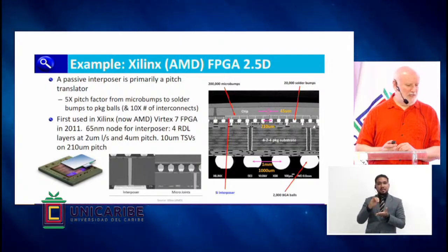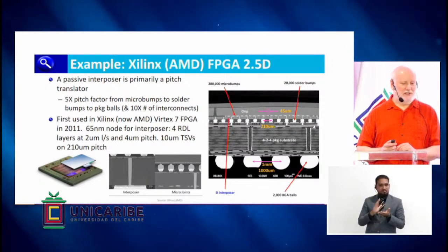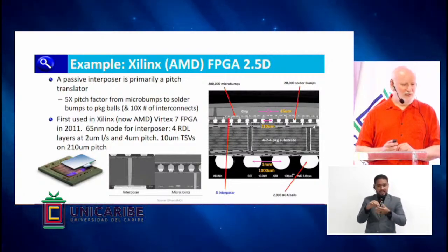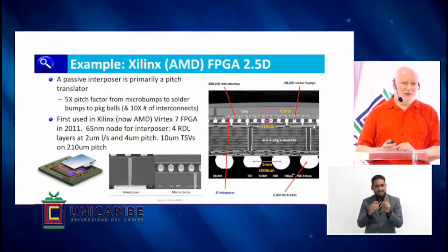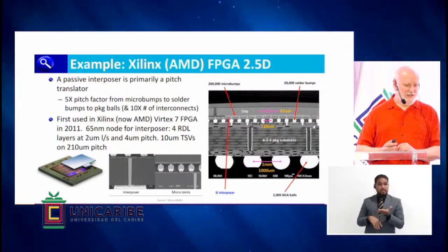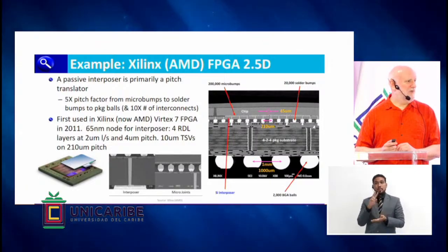At the same time that the pitch is changing, typically the numbers of interconnects are changing. You can see on the chip there's 200,000 microbumps, on the interposer there's 10,000 solder bumps, and then on the package there's 2,000 BGA, or ball grid array, balls. Over my career it's been pretty astounding to see the density increase in interconnects at the packaging level. When I started out, a chip with 1,000 interconnects was pretty dense. Now we're looking at chips that easily have, in this case, 200,000, sometimes 400,000, 500,000 interconnects on them. It's pretty astounding.